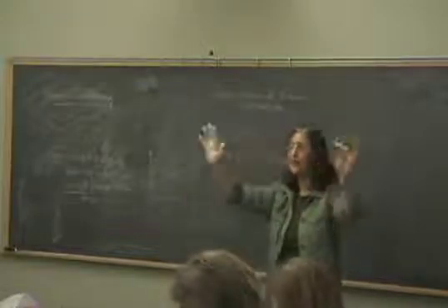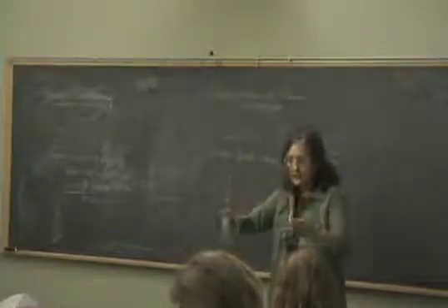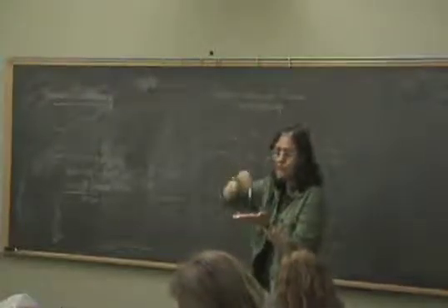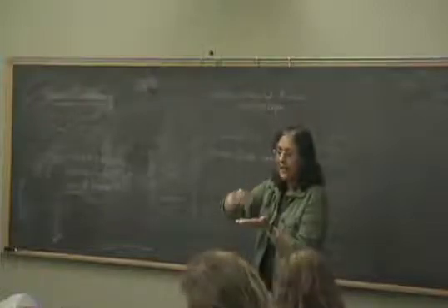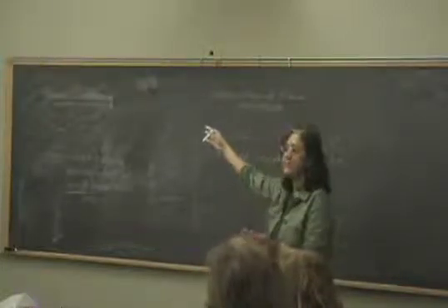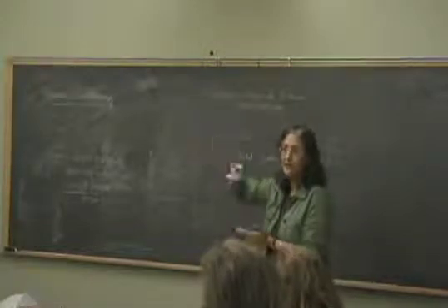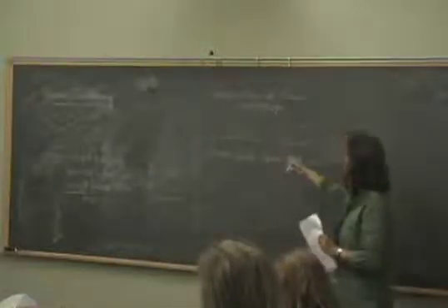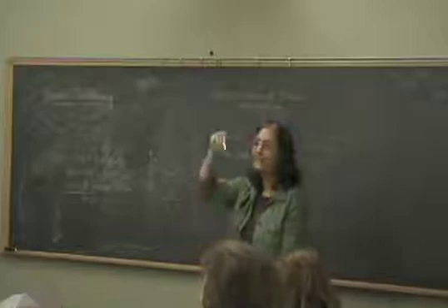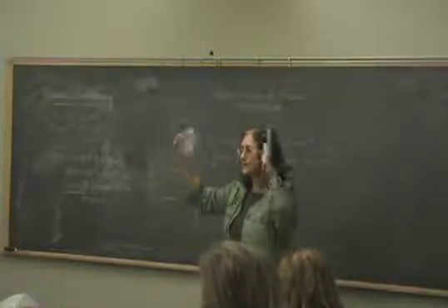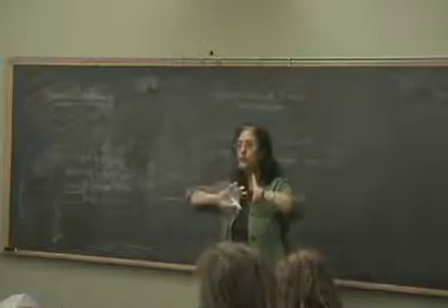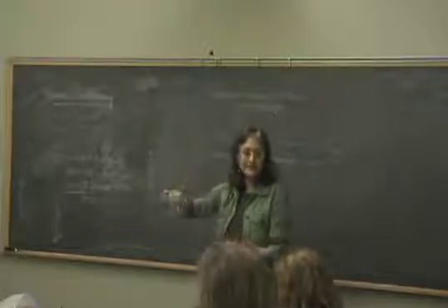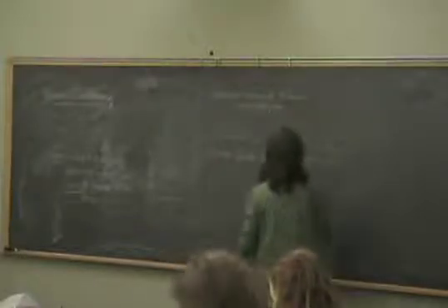Previously, you just had a plane wave hitting the system. You could excite the modes, but the amplitude was very small. Now you have a very strong electric field, and that can give signals which are 1,000,000 times more intense than ordinary Raman scattering. So you have a very large signal to noise ratio. That's the main way this is being used. And the other point is it's a scanning probe. Previously you had light coming in, it would excite something, but you got a global response. Now you can excite things point by point, just using this lightning rod effect near a tip.